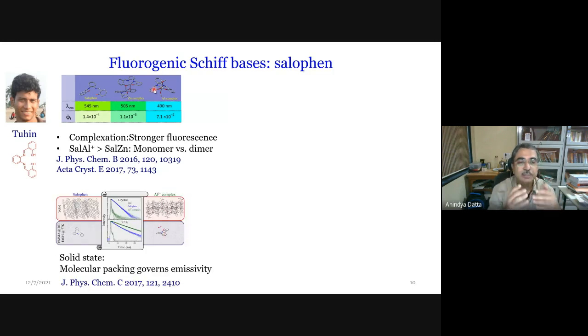So what we did is we made crystals wherever possible, or we made thin films in solid, and we tried to see what happens. What happens is interesting. Salophen, which has a picosecond lifetime in solution, has a nanosecond lifetime in its crystalline form. The aluminum complex, which has a nanosecond lifetime in solution, has a picosecond lifetime in crystalline form. That is because when you look at the crystal structure, upon complexation with aluminum, salophen becomes planarized, and this is how the planarized complexes stack in the crystals. So this seems to be circumstantial evidence for our hypothesis that in this kind of molecules, pi stacking kills fluorescence to a large extent.